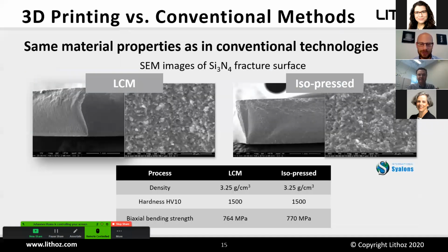Here, to really compare two different manufacturing approaches with one of the most difficult materials, silicon nitride. On the left-hand side, we have the LCM technology. Right-hand side, we have the isopressed. And basically what you see is that there is no difference, either in density, in hardness, or in biaxial strength, it's the same. And even in microstructure, you cannot tell that the left one has been 3D printed or not. So I think this is really a very important approach, that we are achieving the same material properties as in conventional forming technology.